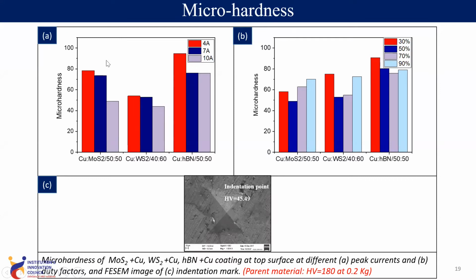These hardness values are due to solid lubricant powder. Basically, the solid lubricant is a soft powder that results in low hardness. These are the soft lubricants, MoS2, HBN, that we are using. So hardness becomes low. That also proves that there is a solid lubricant deposition on the workpiece surface that can improve the tribological properties.